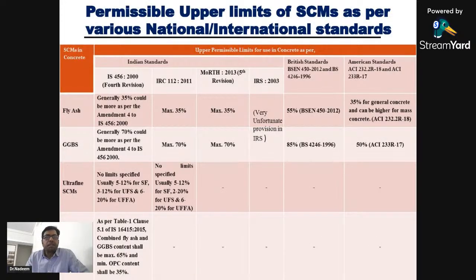In terms of permissible upper limits of SCMs, so fly ash, we have upper limit of say 35%. GGBS upper limit is 70%. Ultrafine SCMs, of course, those materials come under the head of fly ash or GGBS, but normally it is used in the range of say 5 to 12%. Maybe ultrafine GGBS or alcofine or silica fume. Normally, the dosages are in the form of say 7 to 8%, which gives quite a good result along with supplementary cementitious material and OPC.